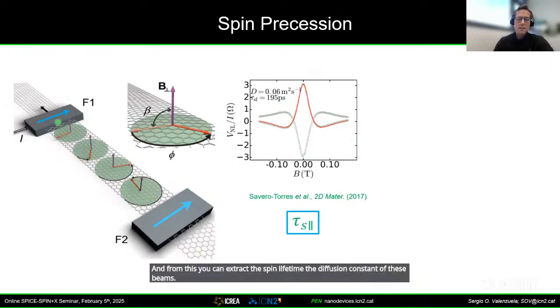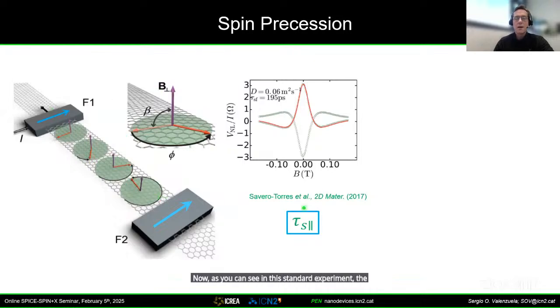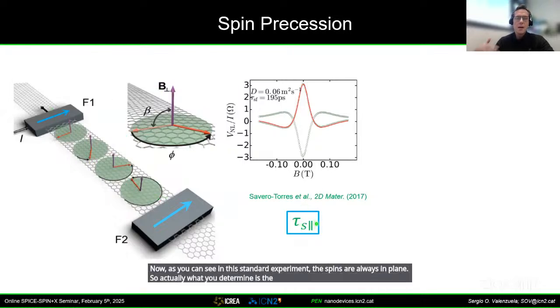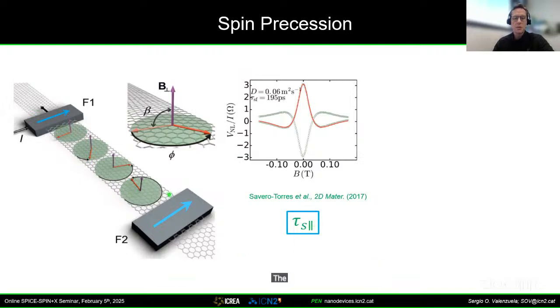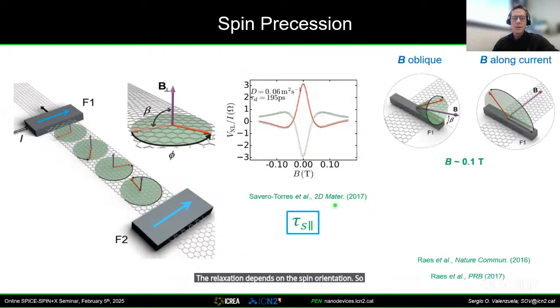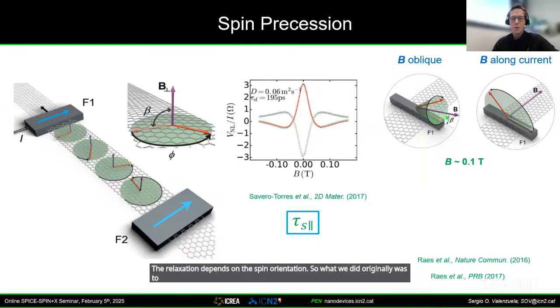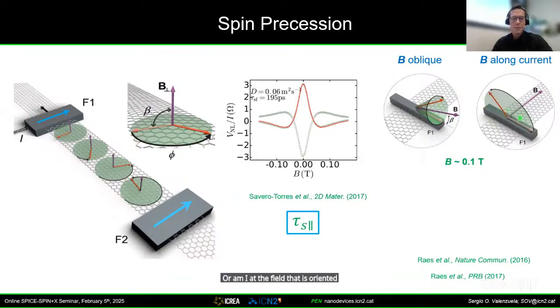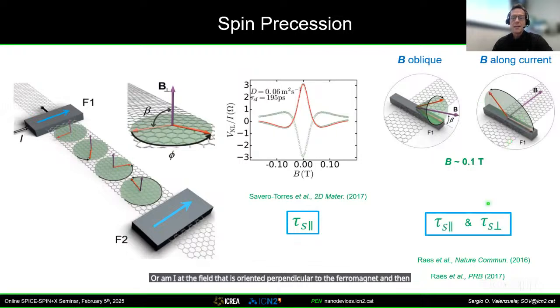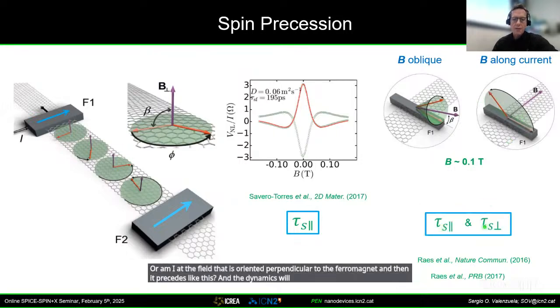Now, as you can see in this standard experiment, the spins are always in plane. So actually what you determine is the spin lifetime in plane. Before, this was not important because the systems were isotropic, but now it's important. Maybe in graphene, the relaxation depends on the spin orientation. So what we did originally was to take the spins out of plane. It's a very simple experiment in which we apply an oblique magnetic field like that, or a magnetic field that is oriented perpendicular to the ferromagnet, and then they precess like this. The dynamics will depend on both the spin lifetime out of plane and in plane. And this is described in these two papers.